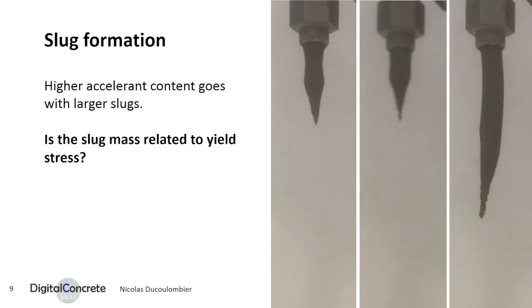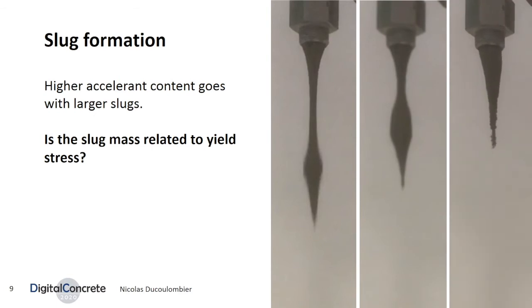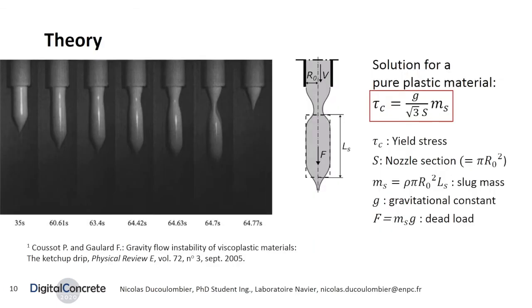They are in fact generated by a discontinuous flow that occurs at the nozzle exit, shown in the video. First experiments showed that higher accelerator content introduced in the printing head during the extrusion goes with longer slugs. The question is then to settle if the slug mass change actually comes from the modification of the yield stress at the nozzle level. The answer is yes for food industry yield stress fluids such as ketchup or mayonnaise.